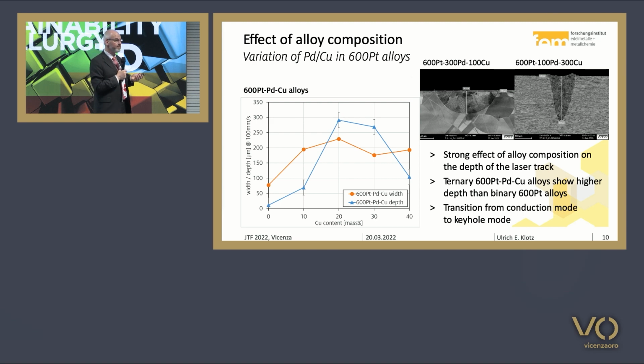So we see that the alloy composition has a strong effect on the depth of these laser tracks, and this is important because we have to melt layers together, so we have to assure that each layer is melted perfectly to the layer below. But on the other hand, if the energy input is too high, we can get porosity inside the material during the keyhole effect.